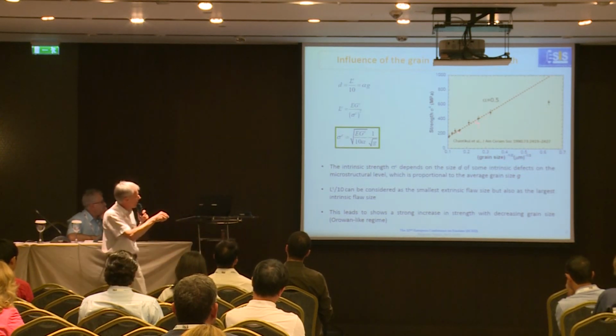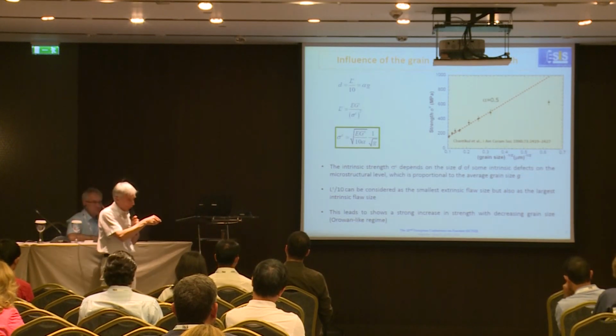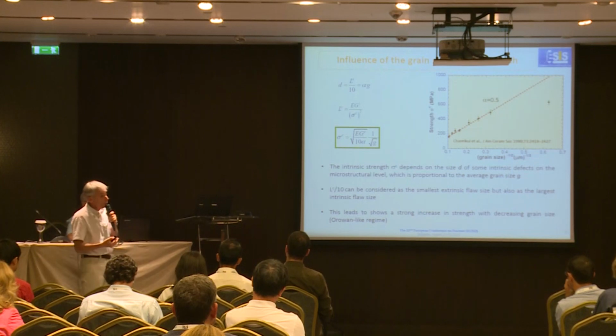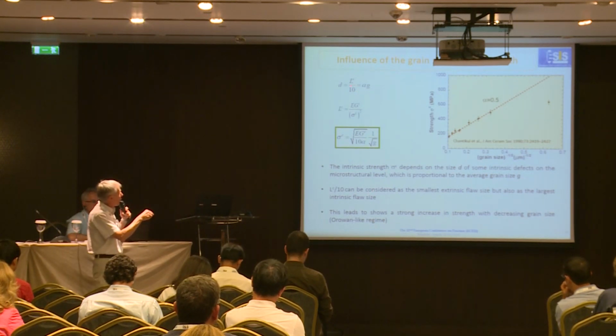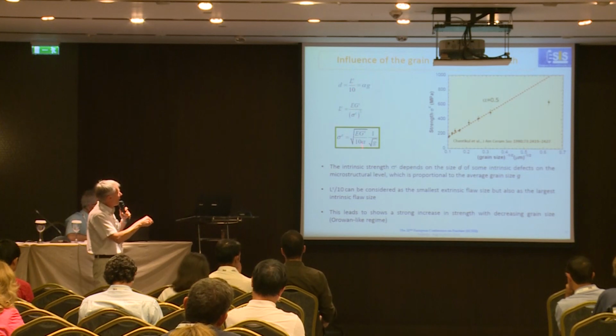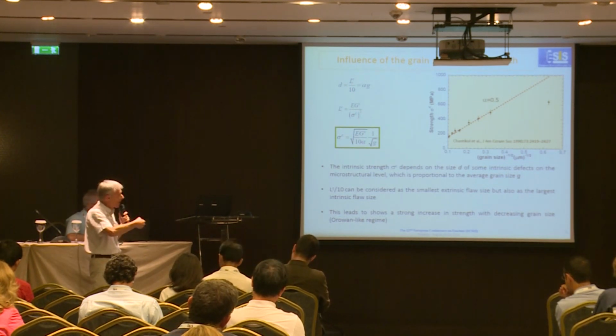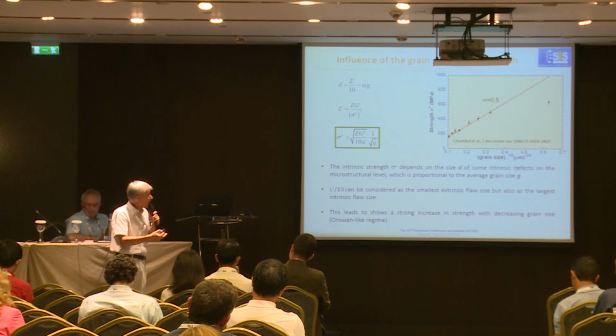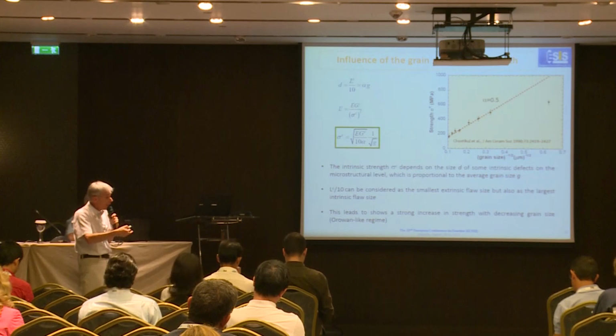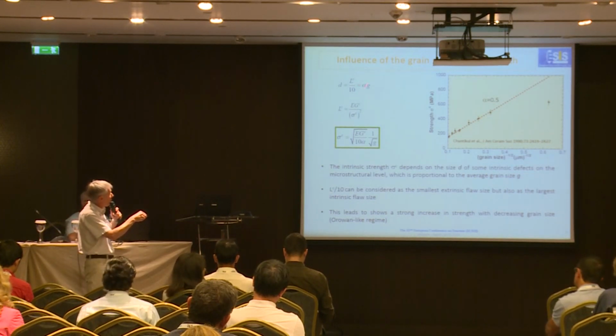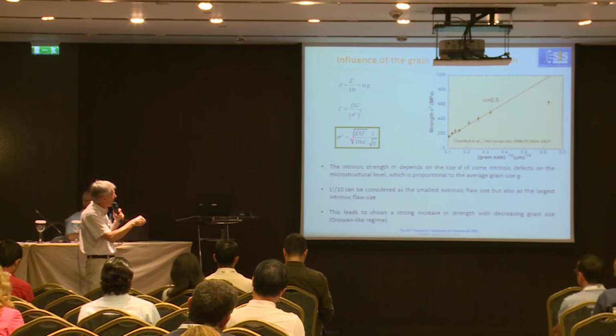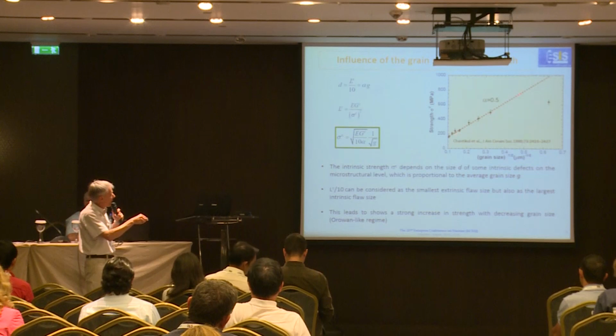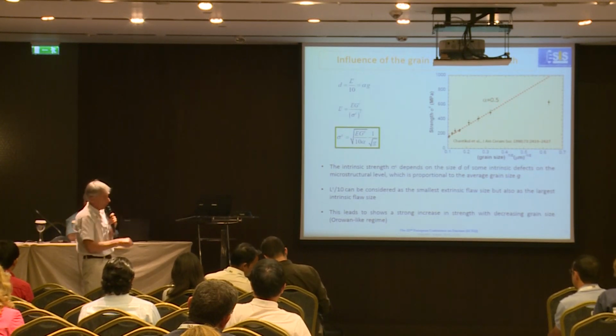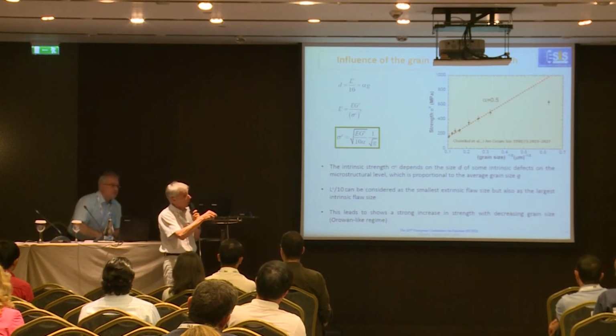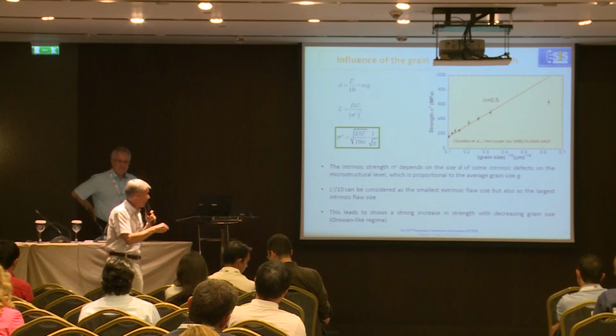This is known as the Hall-Petch-like branch of this graph. Okay, so this is quite easy to recover those experimental data. We have just pointed out that this limit LC over 10 is the smallest extrinsic flaw size, but we also have to consider it is the largest intrinsic flaw size, which depends on the grain size through a factor alpha. So you manipulate this, you obtain this, and you plot this straight curve if you assume that alpha is 0.5. So we are able to recover the Hall-Petch-like branch with the coupled criterion.